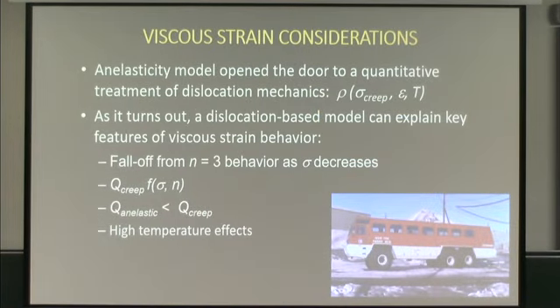So just a real quick consideration of viscous straining here. I'm not going to get into what's been used a lot, other than Erlen referred to an n equals 3 power law dependence, Glen's law it's typically called. Very empirical, and it applies under certain conditions. As in when the dislocation density is really low to begin with, you can get n equals 3 behavior to arbitrarily low stresses. For sea ice, that's not the case. You have a high threshold level of dislocations. That basically makes this a linear problem up to some arbitrarily higher stress.